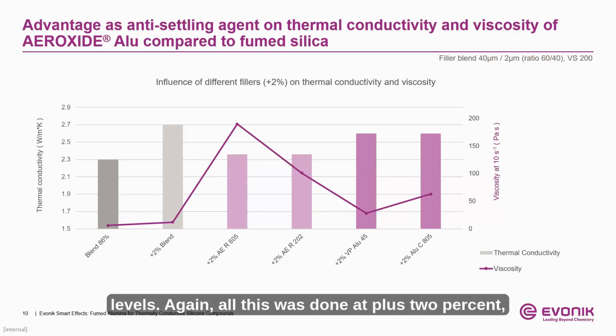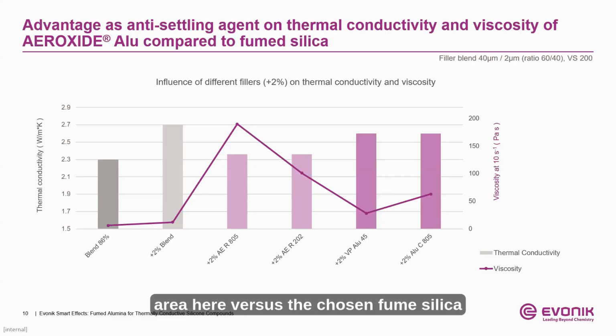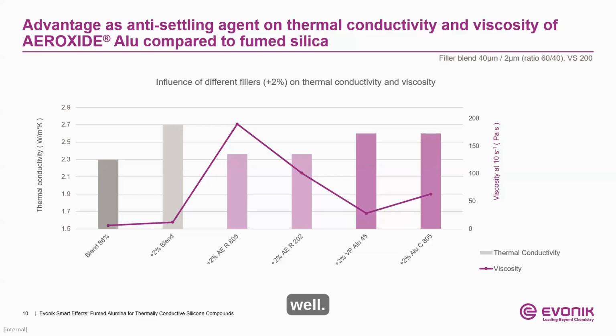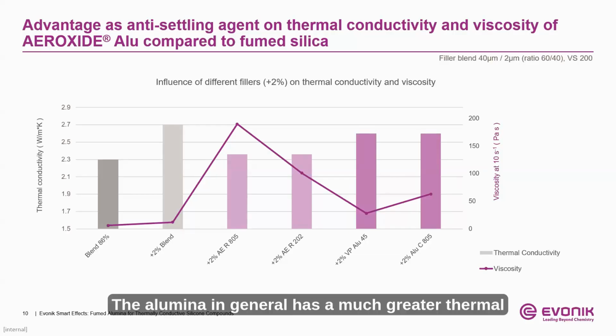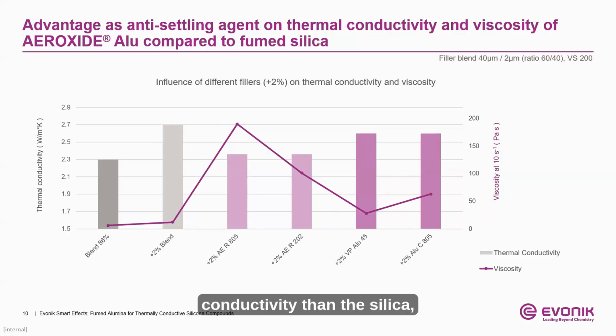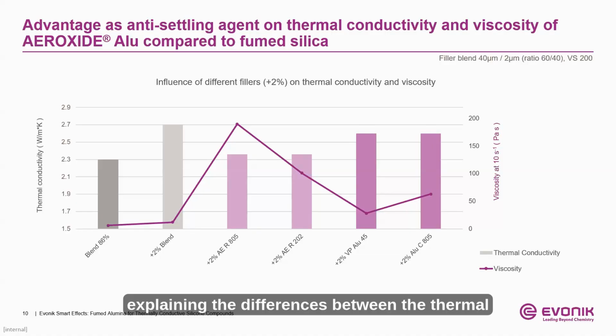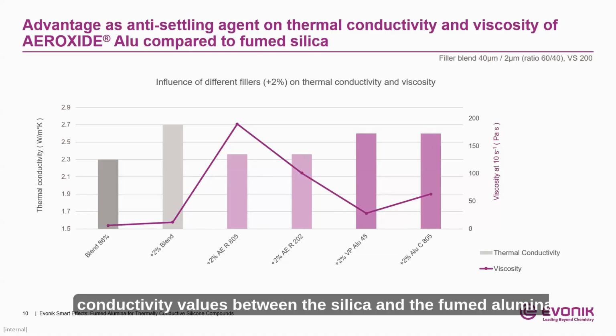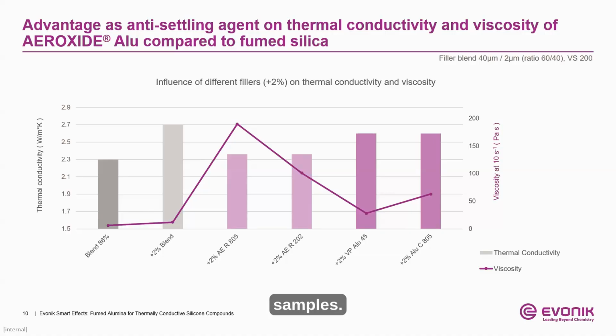Again, all this was done at plus 2%, owing to the much lower specific surface area here versus the chosen fumed silica materials. More importantly, however, is the overall thermal conductivity of the fumed alumina containing samples versus both the fumed silica samples and the blank samples as well. The alumina in general has a much greater thermal conductivity than the silica, explaining the differences between the thermal conductivity values between the silica and the fumed alumina samples.